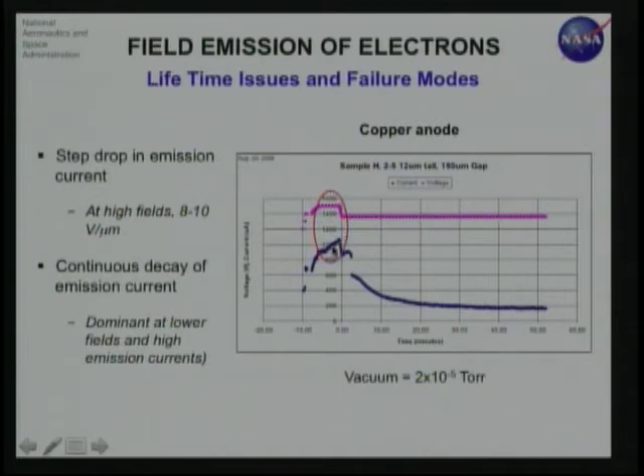And the reason why this happens is nanotubes are not very firmly adhered to the surface. So their adhesion strength, if you measure without doing any surface modification, tends to be in the range of a few tenths of kilopascals. So it's very easy to draw them out when you are applying a field of 8 to 10 volts per micron.